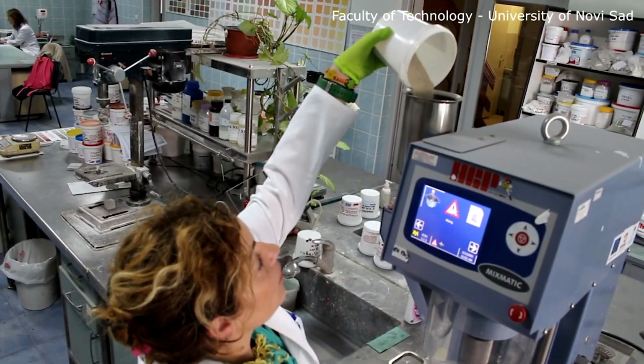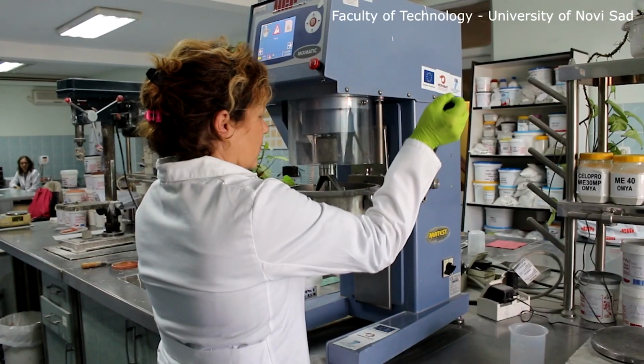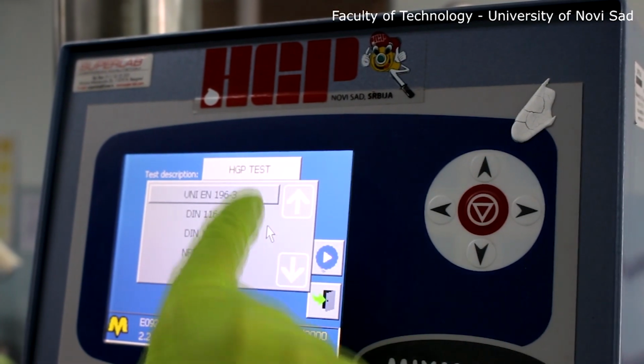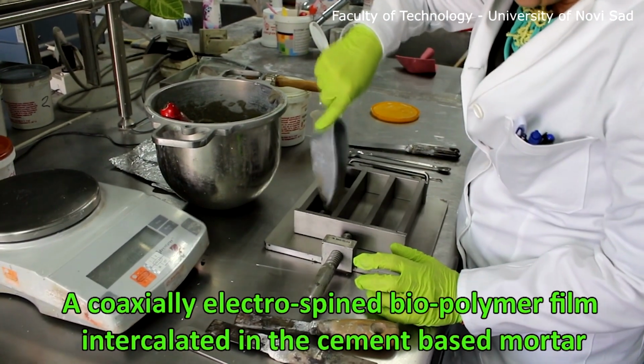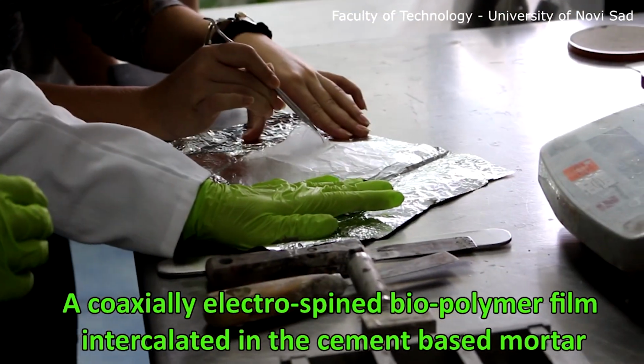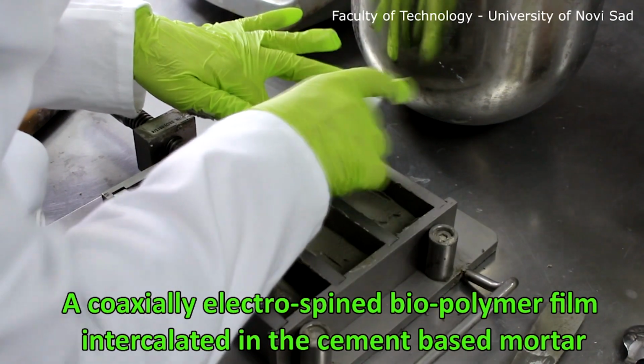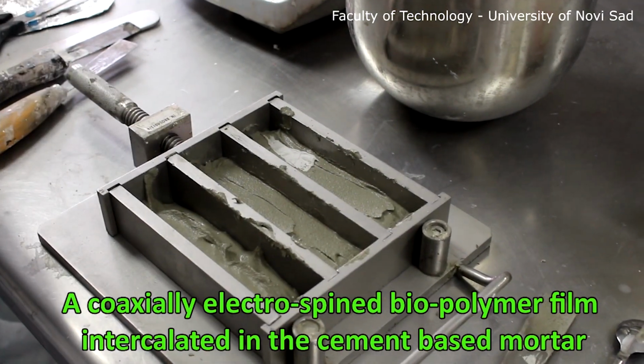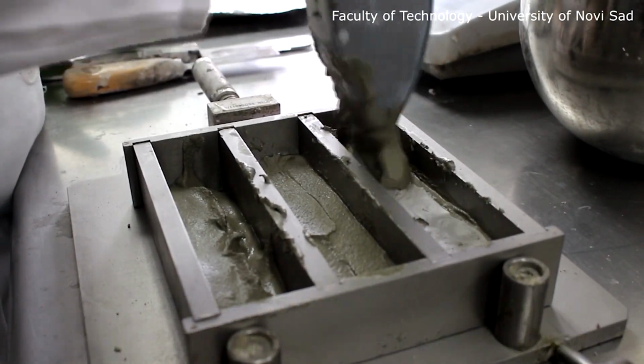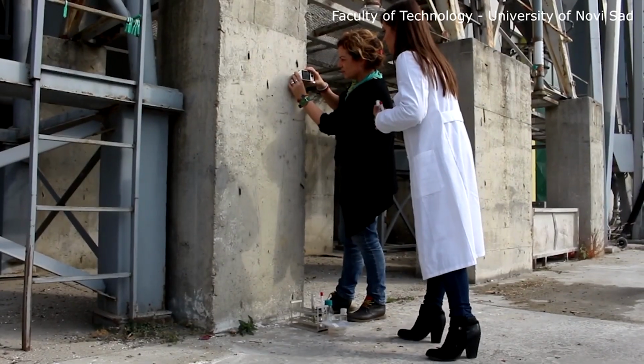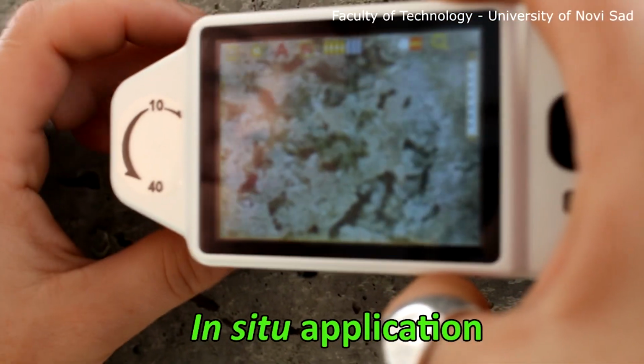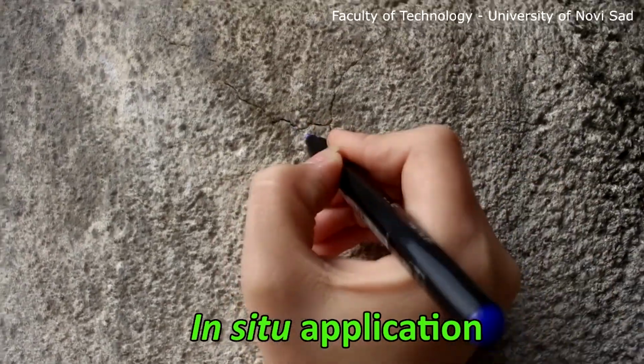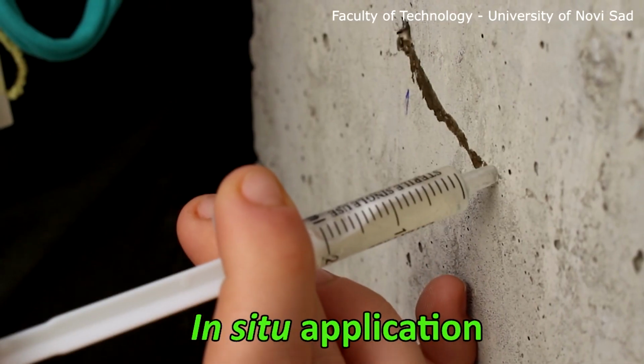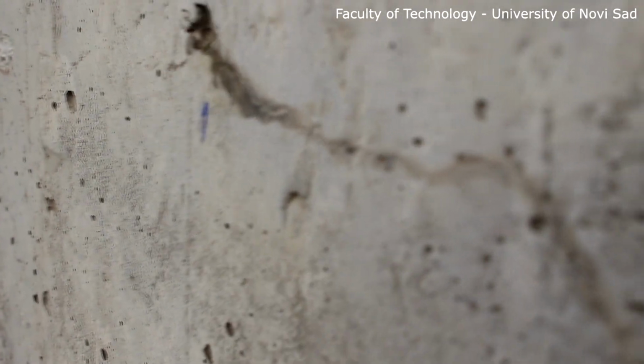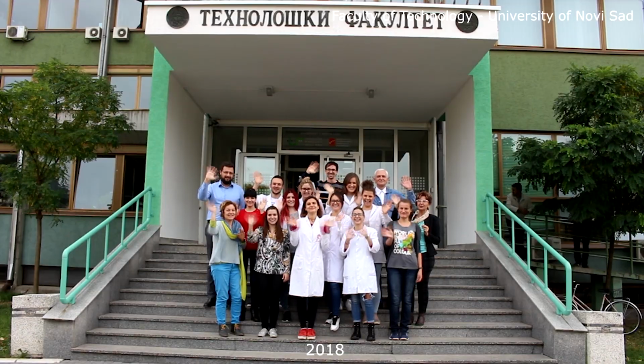Therefore, to protect the bacteria from its surroundings, they propose using a cutting-edge technology, coaxial electrospinning method, for encapsulating the bacteria healing agent in a polymer hydrogel system. The microstructure and texture analysis, 3-point bending tests, water sorption tests, and crack width change measurements showed the effects of healing on the recovery of performance. Besides these activities, their team regularly perform in situ characterization of materials in cultural heritage objects, enhancing the expertise for their restoration, conservation, and protection.